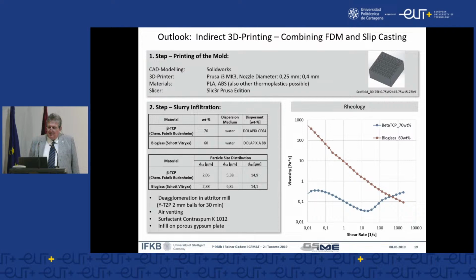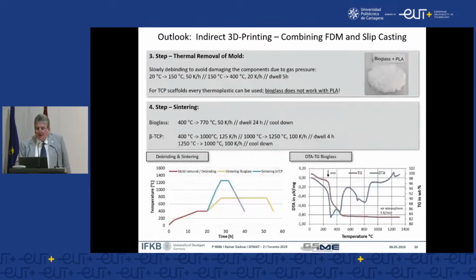And you see, for example, the bioglass has a very high viscosity. If you stir it, or you use another magnetic device, for example, to reduce the viscosity, it works well. The beta TCP had a low viscosity, more or less independent from the shear rate. That means the material was very easy to handle and to manage. And that was the reason why his focus was so strong on the tricalcium phosphate materials.